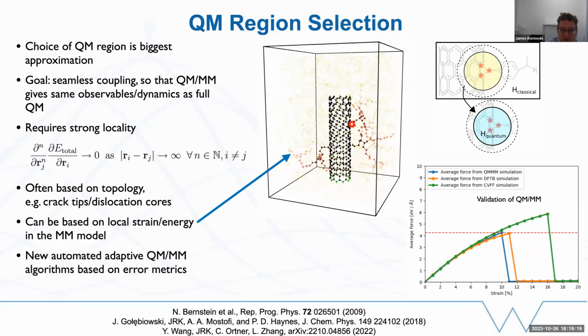And it would be very expensive to model the entire system accurately in order to capture those bond breaking events. So what we did in this case was have many small quantum regions centered on all of the bonds joining the polymer matrix with the nanotube. And actually, we were able to validate that very nicely in this case. So we did a one-off, very large calculation with an approximate quantum mechanical method, a tight binding method, density functional tight binding.